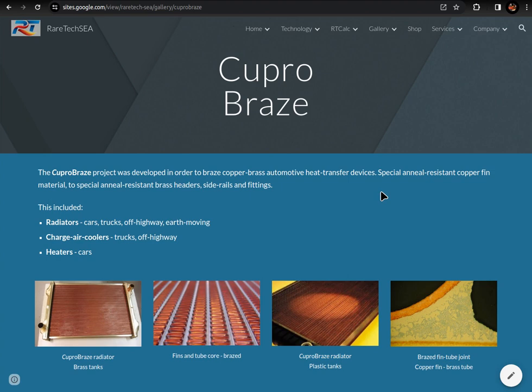And then the tubes, they also put a different type of ingredient to actually control grain growth, because what happens is as you raise temperature, the grains start to grow, and then you end up with basically a very weak structure. So they had to control that in the brass materials as well. And another special complication was that brass actually has zinc in it, and zinc causes all kinds of complications when it comes to brazing, because you're forming a zinc oxide, especially at those elevated temperatures. So we had to be quite careful. Anyway, I'll get into more detail as we go through.